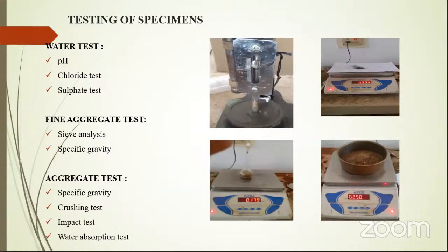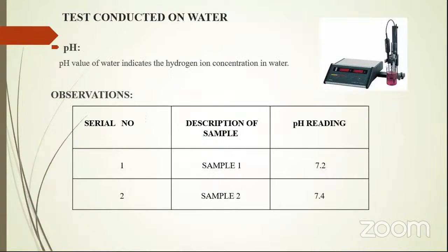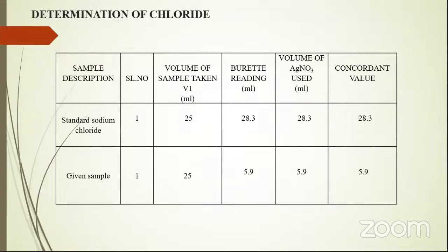Next, the tests we used to find the bond strength and corrosion: water test, pH, chloride test, sulfate test. In fine aggregate, we use sieve analysis and specific gravity. In aggregate tests, the specific gravity, crushing test, impact test, and water absorption tests were conducted. In water, the pH value indicates hydrogen ion concentration in water. For our water testing, the pH reading is about 7.2 to 7.4.